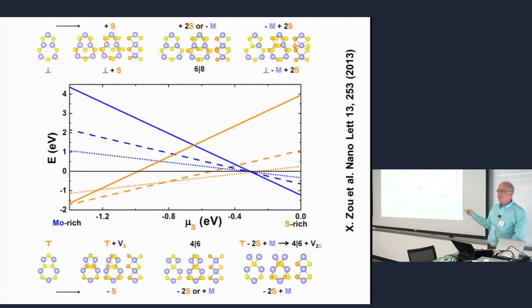And then again, same story, because you can change the local chemistry, right? When Burger's vector is fixed, it's topological invariant. You still can locally remove sulfur, remove 2 sulfurs, you can add metal and so on. So in fact, for one family, and these are reversible processes because they're local. You don't need to rebuild lattice. You cannot jump from here to here because Burger's vector is opposite. But within the family, you have 1, 2, 3, 4 possibilities.